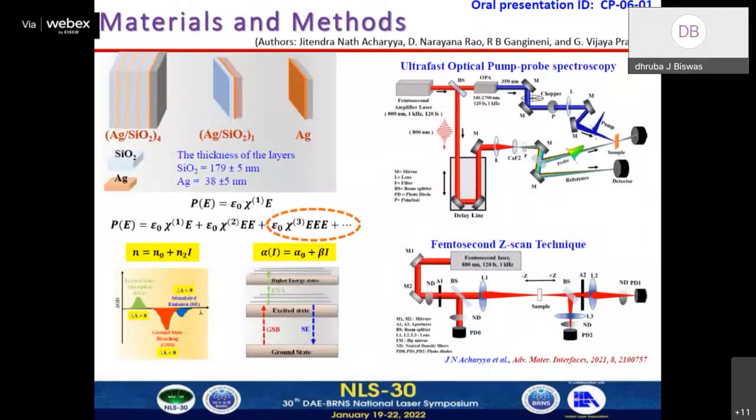Sorry, previous one, please. Four bilayer structures, SiO2, one bilayer, and single Ag film. So we'll focus on the third order and higher order optical nonlinearity and ultrafast dynamics. To study the ultrafast dynamics, we implemented femtosecond pump probe spectroscopy, where a pump beam is divided into two parts, acting as a pump beam which excites the sample, and the other part of the beam is focused on a calcium fluoride crystal to generate a broadband supercontinuum to monitor the pump-induced modification inside the structure.